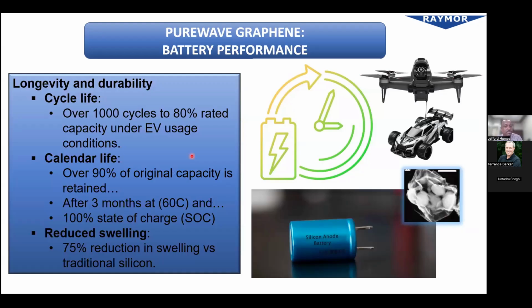In terms of longevity and durability, the cycle life has also been great, over 1,000 cycles to 80% rated capacity under EV usage conditions. And when it comes to calendar life, over 90% of the original capacity is retained after 3 months at 60°C at 100% state of charge. As stated earlier, the use of our graphene has reduced swelling significantly, a 75% reduction in swelling versus traditional silicon, making these types of batteries ideal for first-person view drones, radio-controlled vehicles, and any type of high-drain electronics in general.